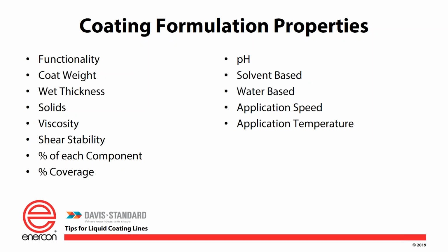But during the drying process and the application, what's that thickness going to be? And what are we putting on? We figure this wet film thickness out based on the solids content of that coating and the actual amount of coating you're asking for. And then density will actually play a part of that. Most of your adhesives are slightly above a 1. Water is a 1 density. Adhesives are like a 1.1, slightly heavier.